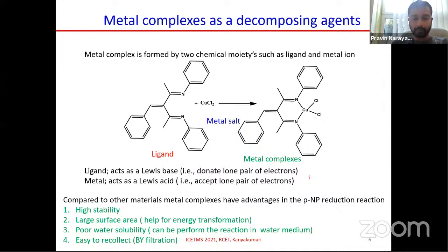stable and large surface area, which help the energy transformation in the catalytic process. And most of the metal complexes have poor water solubility, so we are able to perform the reaction in a water medium, and since the metal complex is not soluble in water, it is very easy to recollect and reuse by a simple filtration technique.